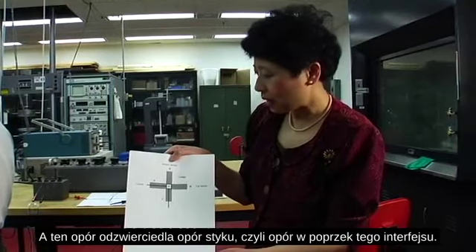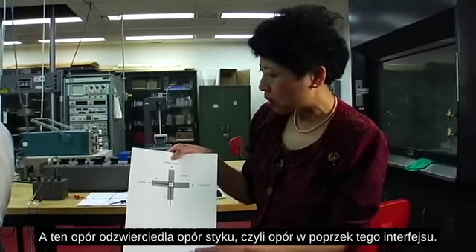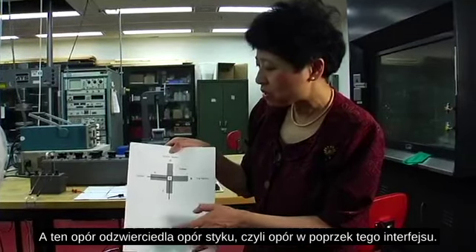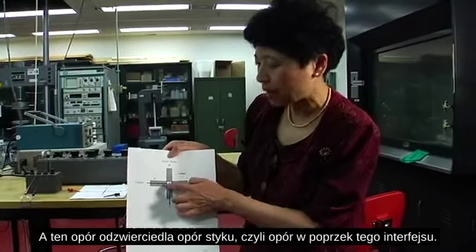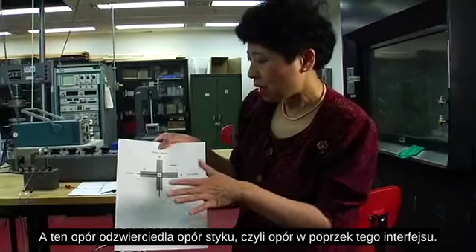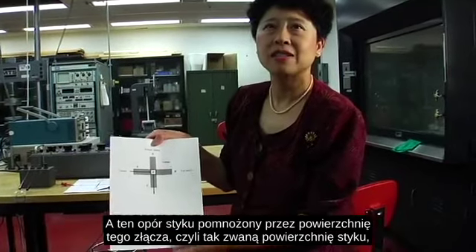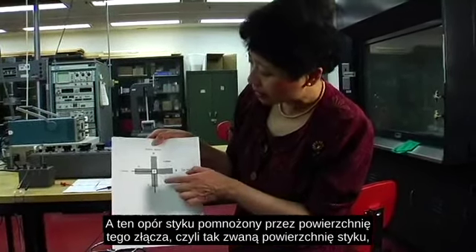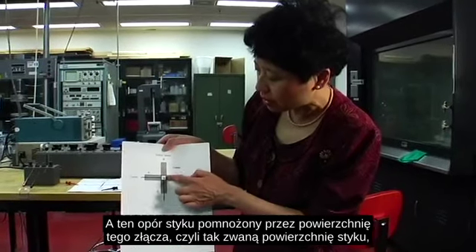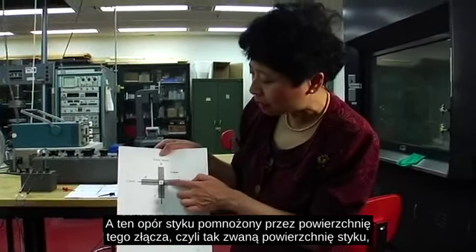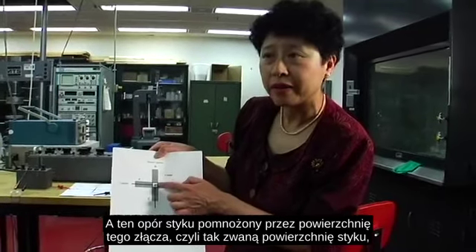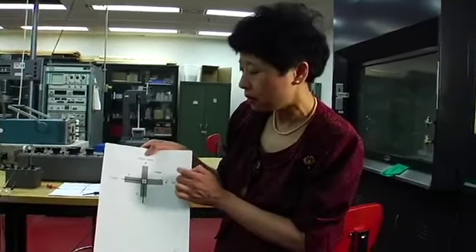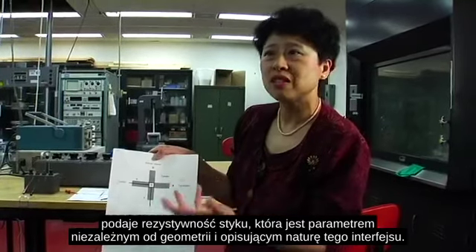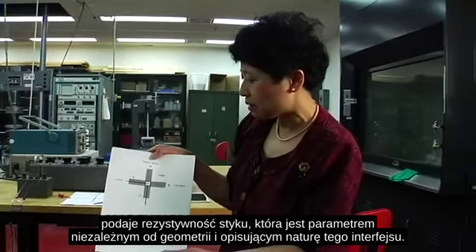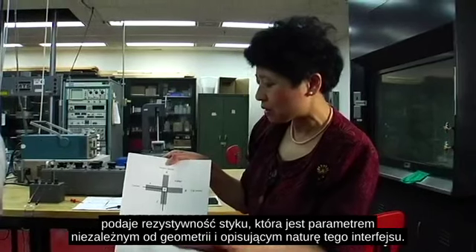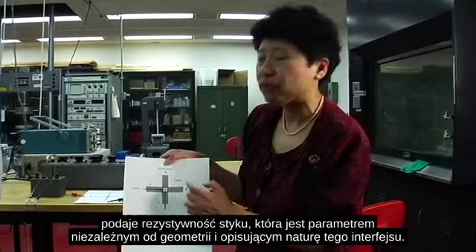And this resistance reflects the contact resistance, which is the resistance across this interface. And this contact resistance multiplied by this junction's area, what's called the contact area, gives the contact resistivity, which is a geometry independent parameter that describes the nature of this interface.